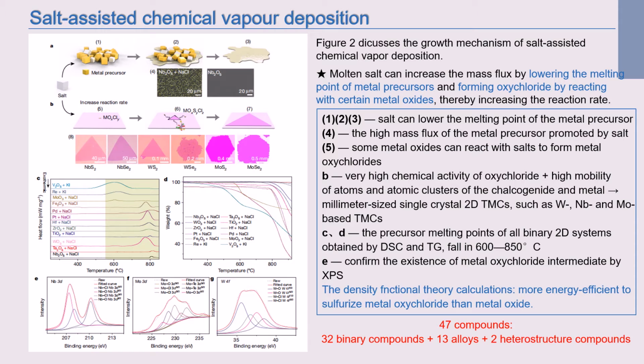Figure 2b also shows that during the growth process, the coarsening forms a stable nucleus, and then atoms and atomic clusters of the chalcogenide and metal are attached to the edges of the growing monolayer film and grow rapidly due to their high mobility and proper temperature. Another reason for the rapid growth is that the chemical activity of oxychloride is very high during the reaction. This helps to produce millimeter-sized single crystal 2D TMCs, such as tungsten, niobium, and molybdenum-based TMCs. Also, the density functional theory calculations show that it is more energy efficient to sulfurize metal oxychloride than metal oxide.